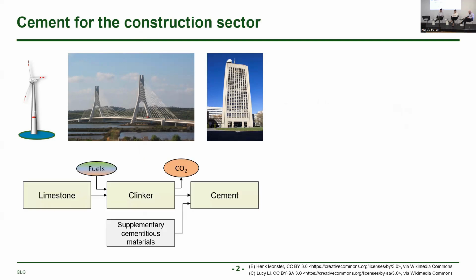In a very simplified way, we can say that for Portland cement, we use limestone that is then used to produce clinker. There are lots of chemical reactions going on, a high temperature process, we've heard earlier, 800 to 1000 degrees Celsius. The limestone is decomposed into carbon dioxide, which is the process-related emissions, but then we also have large quantities of carbon dioxide emissions from the fuels.